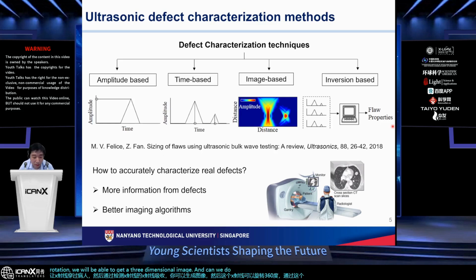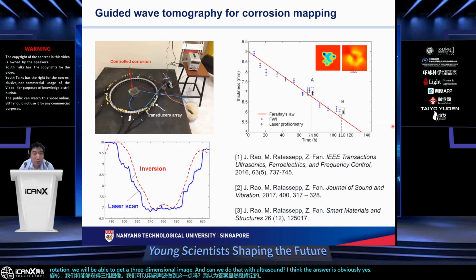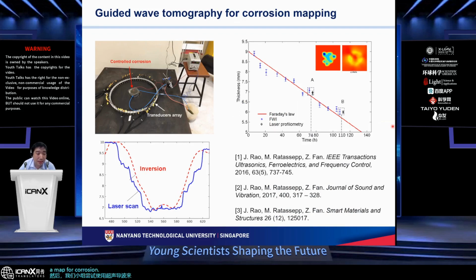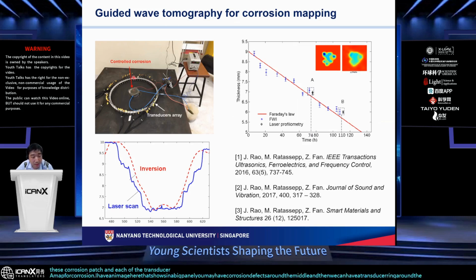And can we do that with ultrasound? I think the answer is obviously yes. We can do ultrasound tomography. This is one of the research works our group has done, trying to use ultrasonic guided waves to map corrosion. I have an image here that shows a big panel where you may have corrosion defects around the middle, and we have a transducer ring around this corrosion patch. Each transducer sends an ultrasonic signal. This signal is in the low frequency range, a few tens of kilohertz up to 100 kilohertz. This is very low frequency.